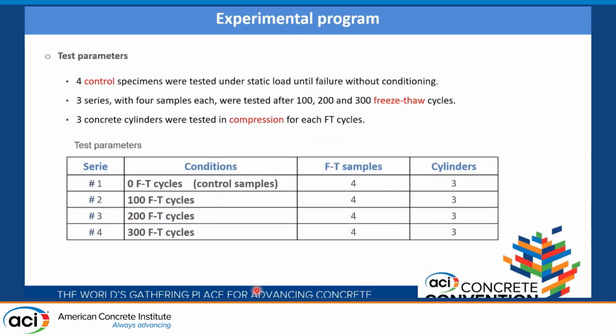For this experimental program, 4 control specimens were tested under static loading until failure without conditioning, to be considered as reference results. 3 series with 4 samples each were tested after 100, 200, and 300 freeze-thaw cycles. In addition, 3 cylinders were tested for each freeze-thaw cycle count.